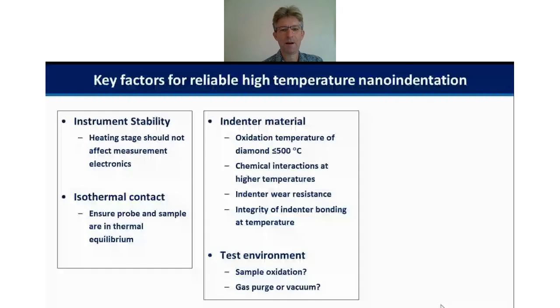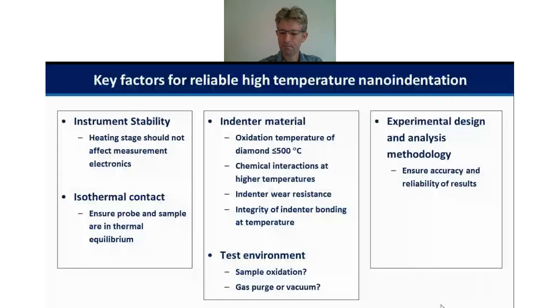You also need to think about the hardness and even potentially the fracture toughness of the indenter material. So again, this may be very different to what it is at room temperature. And you also need to make sure that the indenter remains well bonded into its holder at high temperature. So you may need to use things such as a very high temperature braze or a glass ceramic bond, as we've done at Micromaterials. And also, as I mentioned, the test samples themselves may oxidize, and that also impinges on whether you can get away with an argon purge or whether you need to move towards high vacuum.